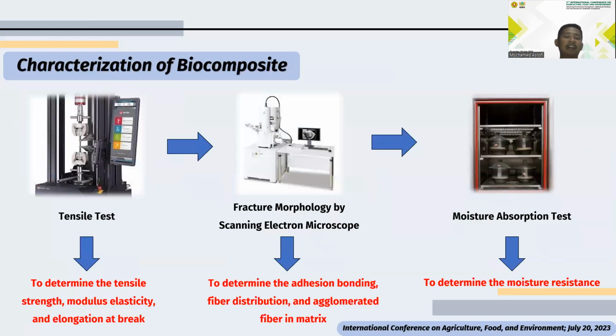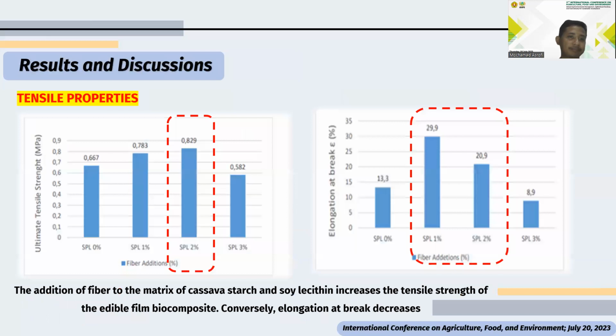And after we got the product, we characterize it. We test with the tensile test to determine the tensile strength, modulus of elasticity, and elongation at break, and also fracture morphology by scanning electron microscope to determine adhesion bonding, fiber distribution, and agglomerate fiber in the matrix. And the last test is the moisture absorption test to determine the moisture resistance.